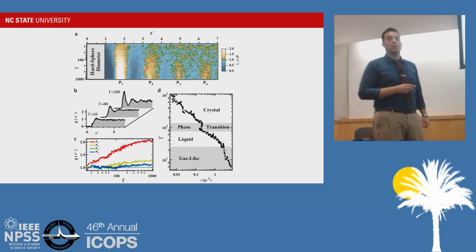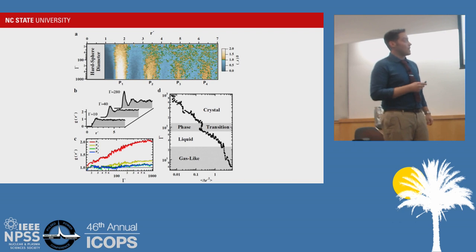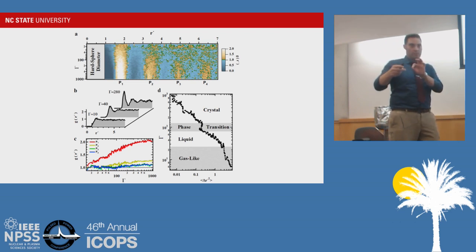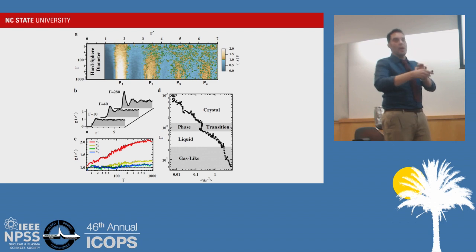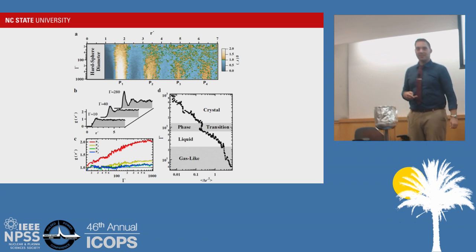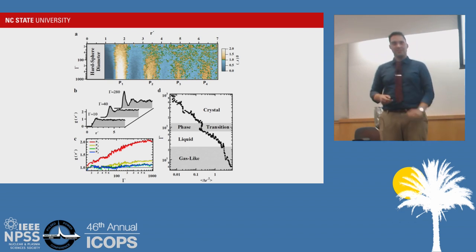What I do is the radial distribution function. That's actually how I was able to figure out whether it's a liquid or a crystal. The radial distribution function has a characteristic signature when it becomes a solid: you see that nice, long, sharp peak, longer-range order. As a function of gamma and the distance away, balls can't overlap, so this region is nothing. Here's your first neighbor, second neighbor, third neighbor, fourth neighbor. Now I'll ask you, what peak do I have to reach to make it a crystal? I'll leave that question to you.